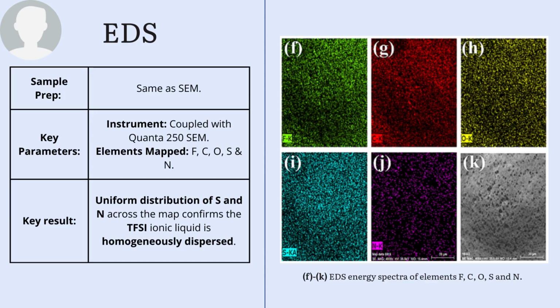So this shown mapping is only for the ratio 2 to 1 of the membrane composite. So observing the maps on the right, specifically the bottom row, a uniform homogeneous distribution of this element is evident across the entire field of view. There is no significant agglomeration or hotspots detected, and this confirms that the solution blending method was successful.